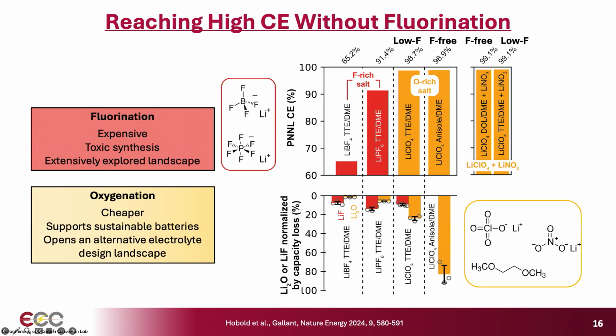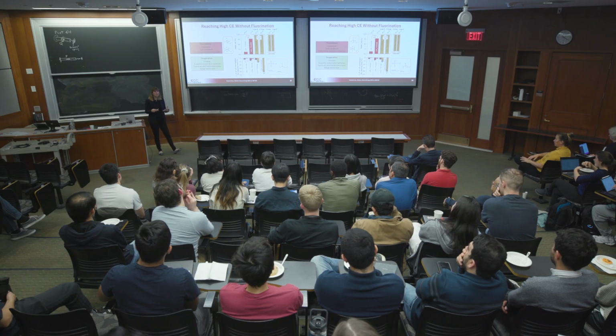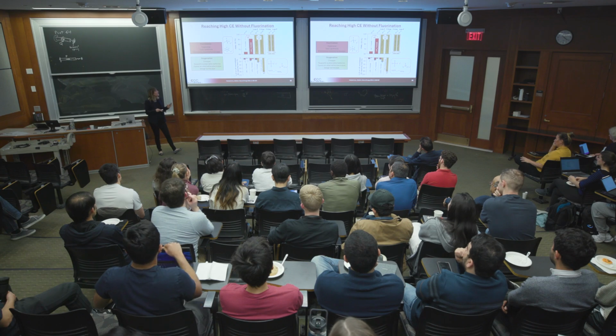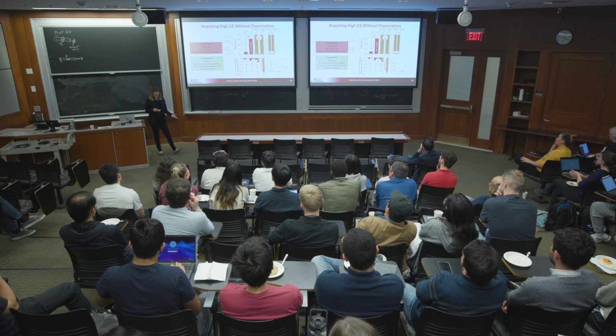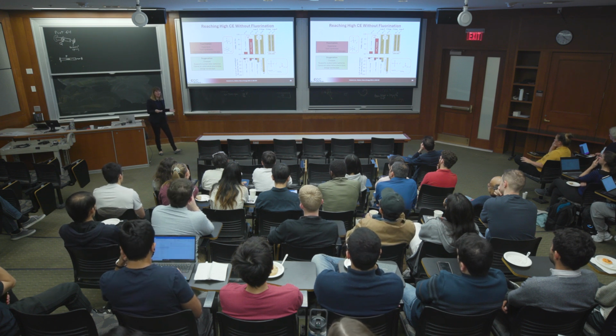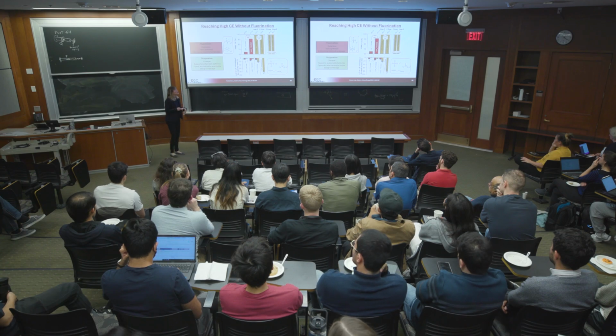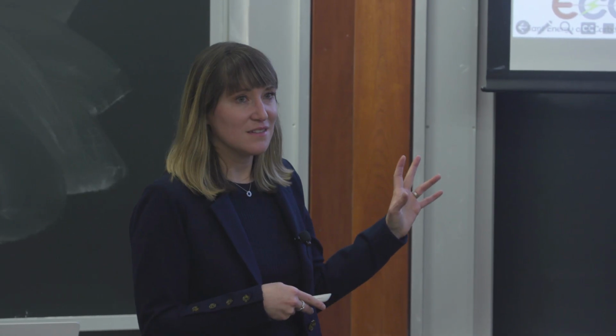And in particular, with this case here, where we have a completely fluorine-free electrolyte, we were able to breach 99% Coulombic efficiency for the first time. Okay, no fluorine. So of course, 99% is not 99.95 or 98%. But this is really exciting. It shows that maybe there's a pathway we have overlooked, and we should invest more time into getting these numbers to be higher. But I think this was very surprising to many in the community that we could even get numbers that start to get into this range.